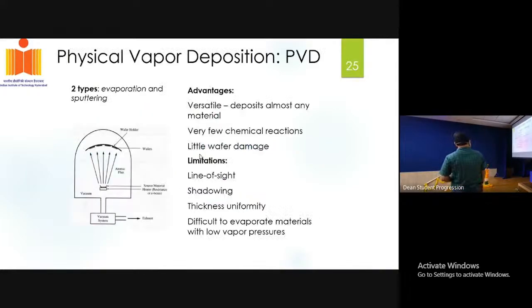So what is meant by physical vapor deposition? You take the material and physically evaporate it. You have the material and you have the substrate here. You evaporate so that this material will go and deposit on top of your substrate. This is one of the important physical vapor deposition techniques, be it thermal evaporation or electron beam evaporation. You have a source, you heat up the source so that the material in the source will evaporate and deposit on top of the substrate, so that you can get the film. Suppose you see a mirror: you are able to see yourself because you have a silver coating on the backside. Such kinds of films you can make using physical vapor deposition.